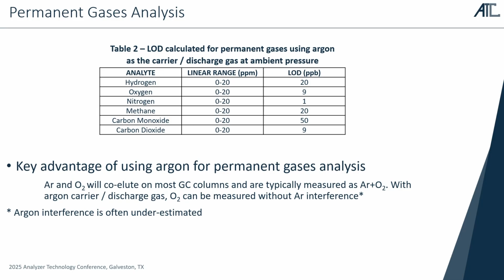Another key advantage of using argon as the carrier gas in this application is that for most applications in ultra-trace level analysis, for the measurement of oxygen, you would actually measure oxygen plus argon because they coelute on most GC columns. So using argon would remove this interference from argon that would coelute with oxygen, because it's going to be hidden by the carrier gas. And it's interesting to note that over the years that we have been doing this test, so many times, we realized that when you measure argon plus oxygen, the amount of argon is often overlooked and you might actually have more argon than oxygen. So if you want to have a very accurate oxygen analysis, it's interesting to go with argon as the carrier gas.